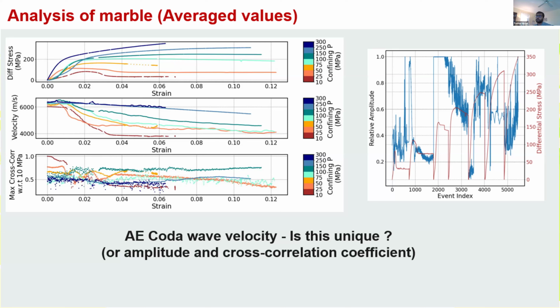Can we pick out where you are just based on velocity, cross-correlation, or amplitude, the peak amplitude or the transmissivity, for instance, of the waveform? We started with these three features of the coda because they have been used previously in a number of studies, again primarily in the friction context, and they have a lot of information about the state of the system. These could potentially even uniquely, in most cases, tell us about the state of the system. So we want to test it, starting with these as a base case and seeing what other information we need, or whether these are enough to distinguish between the different setups, different stress states.